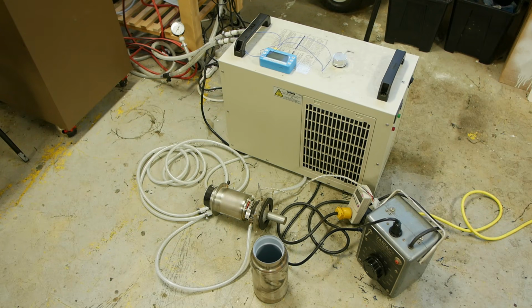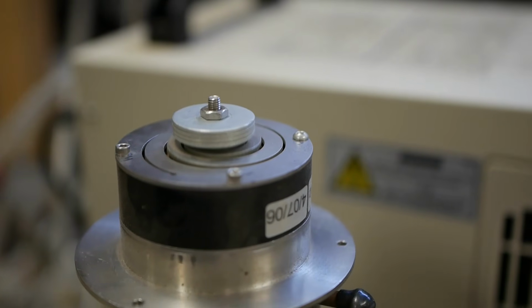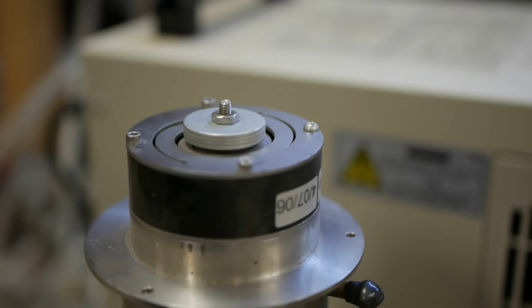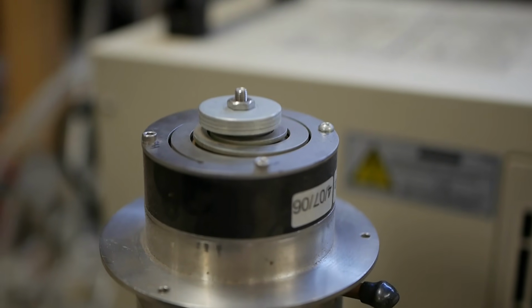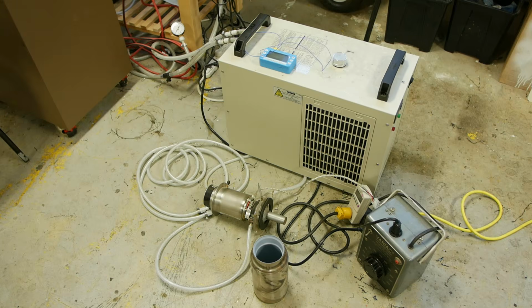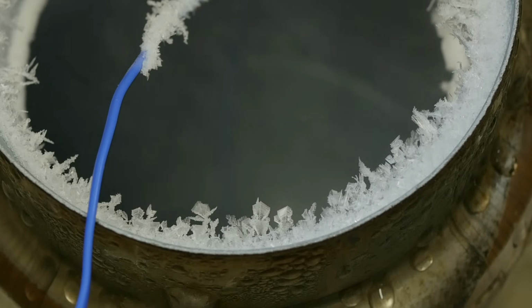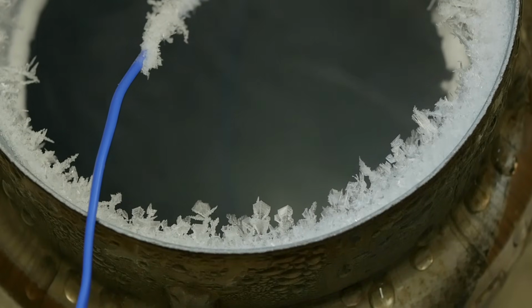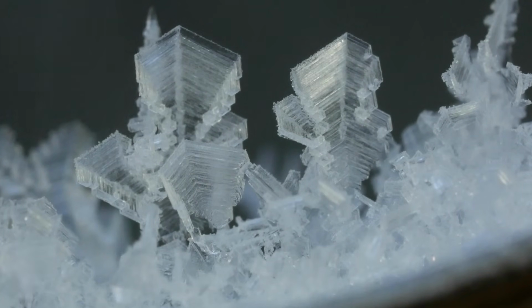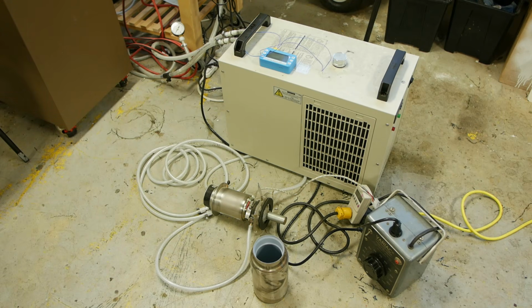If you don't have access to a cryo cooler, heaven forbid, and you're starting with basically a tank of liquid nitrogen, what you want to do is drip it slowly into the thermos so that you don't thermally shock the steel. I get the feeling that this is actually not a huge concern, and you could probably just pour it in kind of slowly so that the liquid nitrogen cools the thermos down a bit, and then pour in a little bit more later or whatever. I didn't experiment with trying to break the steel due to thermal shock, but all of the information on the internet claims you have to cool it down and warm it up slowly.